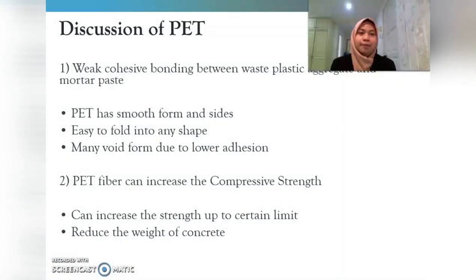Discussion part for PET. As we know, the increase of PET as partial replacement will reduce the strength of concrete. The reason is the weak cohesive bonding between waste plastic aggregate and mortar paste. PET has a smooth form and size, and it is easy to fold into any shape. Next, PET has many voids, forming lower adhesion.